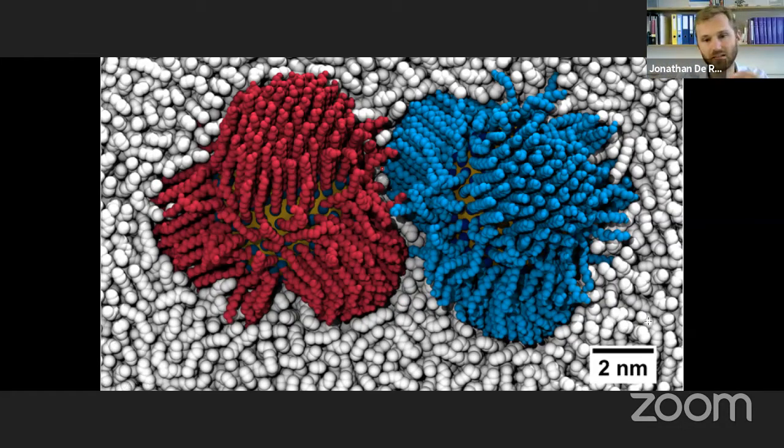And what this picture is showing is one nanocrystal filling up the groove of another nanocrystal with a ligand bundle. And so here again was shown, yes, crystallization of ligands on nanocrystals is what's driving precipitation or dissolution for small nanocrystals.